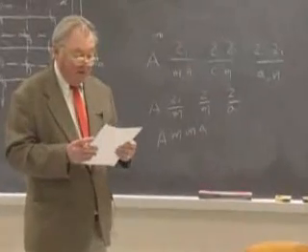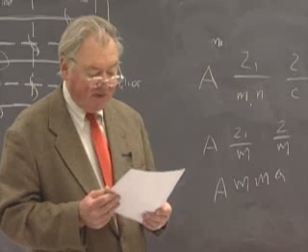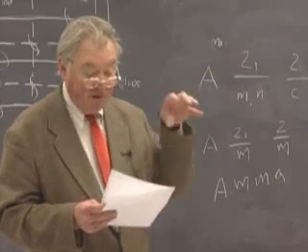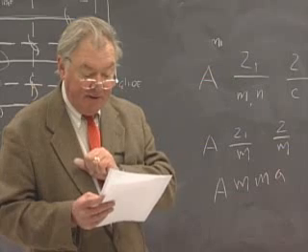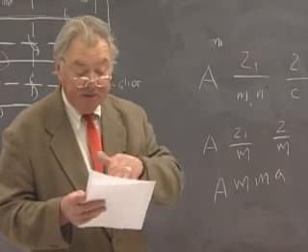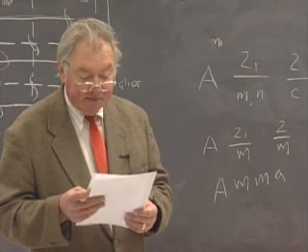And this is something that is analogous to P4MM in 2 dimensions with the fourfold and twofold axes extended parallel to the edge of what is now a tetragonal cell. And then there are twofold axes perpendicular to the fourfold axis. So actually 4 over m, 2 over m, 2 over m has been dropped in at a lattice point of a primitive tetragonal lattice. The chevron in the upper right of the arrangement of symmetry elements is the mirror plane that's perpendicular to the fourfold axes. The other mirror planes are the same as in the plane group P4MM, and the glide plane, which would now be called a diagonal glide, is exactly the same as in the two-dimensional symmetry.